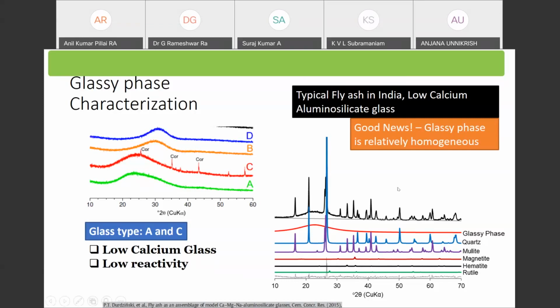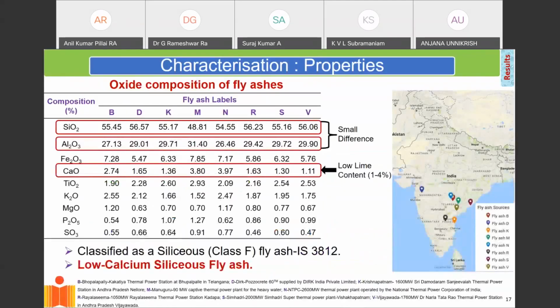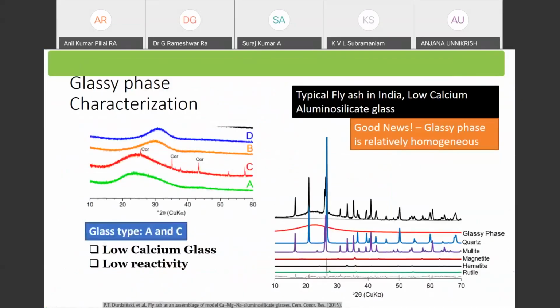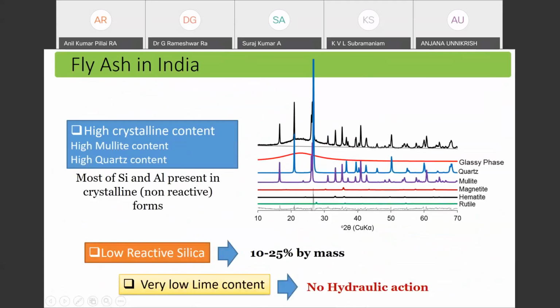The other thing is, I just wanted to show you the X-ray diffraction signature of a fly ash. The black line here shows the X-ray diffraction signature of a typical fly ash. A good percentage of the fly ash contains quartz, the quartz that is shown here. Now, quartz is basically also silica, which is present in a very non-reactive form, in the form of sand. So a lot of our fly ash comes loaded with silica, and what you saw in the table above, the SiO2 that you see, a lot of it is locked in the form of quartz, which is non-reactive. What we need is the amount of silica that is present in this glassy phase, which is shown in the red line. So we developed a methodology to look at the reactive part of the silica of the fly ash, which is present in the glassy form.